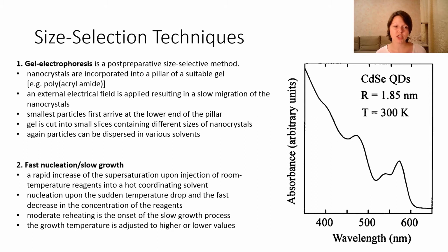And the fast nucleation and slow growth process. Here we have the reduction of the nucleation process to a short time interval upon injection of room temperature reagents into a hot coordinating solvent. Here, a rapid increase of the supersaturation happens.